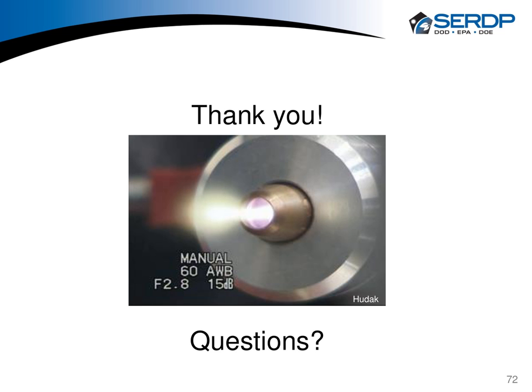One does not have to use an oxidizing plasma for everything. We're trying to remove paint. If one is trying to convert a coating, you can use a reducing plasma. Now, you're right, though. If you use an oxidizing plasma, it will oxidize the surface. In terms of an epoxy graphite composite, yes, it oxidizes the epoxy. When it gets to the graphite fiber, it stops. We had a program with Cherry Point for chrome 6, and we've actually reduced the oxide down to the chrome 3. So we've done some of that work, not extensively.